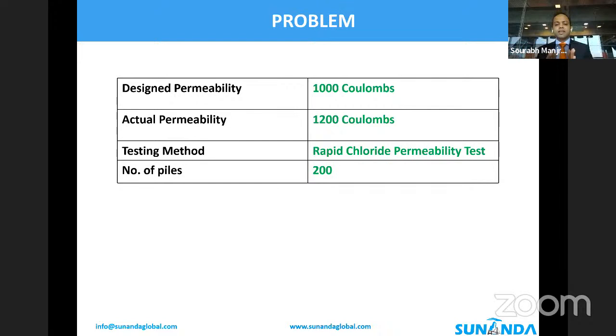We understood the case. We studied the concrete data, RCPT data, the steel configuration, the soil. And then we designed a galvanic sacrificial anode system to protect these rebars. Now, see, you can't do anything to the piles. You cannot give it any sort of coating or barrier as they're embedded. But fortunately, the consultant confirmed that the steel was in complete continuity and the steel was yet exposed on top. And that is why a sacrificial anode system could be designed to compensate for this additional 200 coulombs permeability and yet achieve the desired service life for this particular structure.